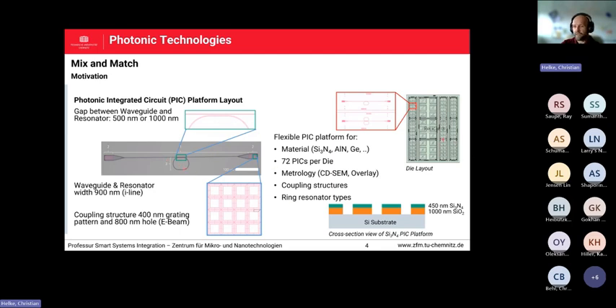On every die, each of these 72 has a different configuration, meaning ring resonators 1, 2, 3, 4, different configuration modes or different in and out coupling structures. And so we decided to use this platform for testing the mix and match process from the lithography point of view, because the waveguide and the ring resonator always have, for example, a 900 nanometer waveguide width. The gap in between is always 500 nanometers or 1000 nanometers, so really nice to have it here with our high throughput I-line stepper lithography tool.